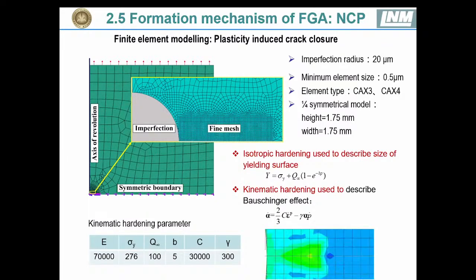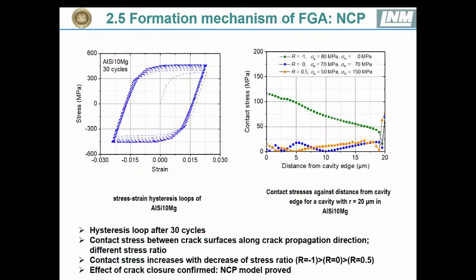And then using this model, we run several cycles, and we try to analyze the contact stress. We can see that the contact stress on the crack surfaces increases with the decrease of stress ratio. And such a quite high contact stress may lead to the grain refinement, and this partly validates the NCP model, that is, the effect of contact stress to make the grain size refinement.